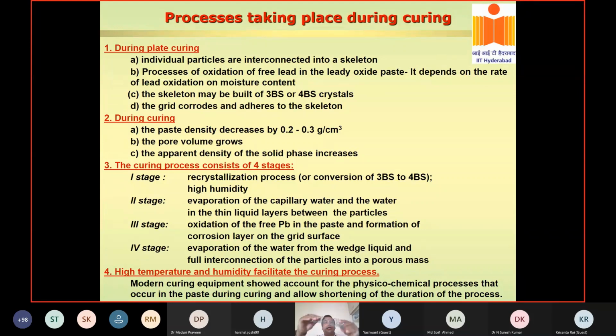And during this period, the corrosion layer also forms. This is also another important process, the corrosion layer. And also the water will evaporate, and you may have interconnected particles into a porous mass. And also the paste density will reduce to some extent. That means you will have a pore volume. That's very, very important, particularly for lead acid battery.